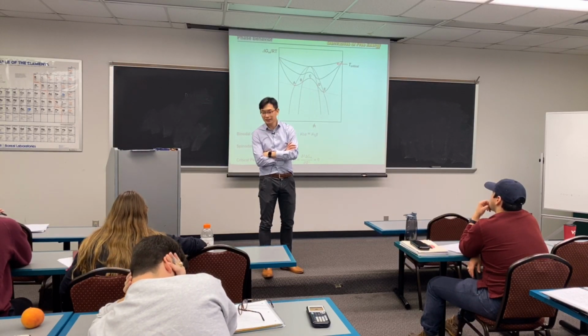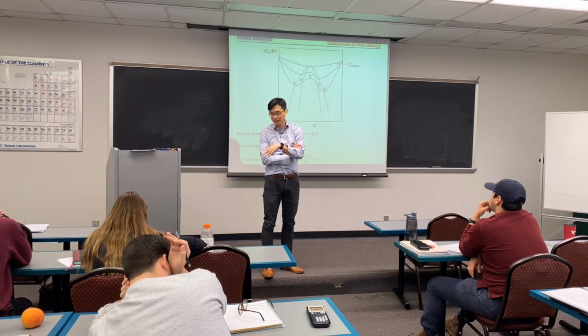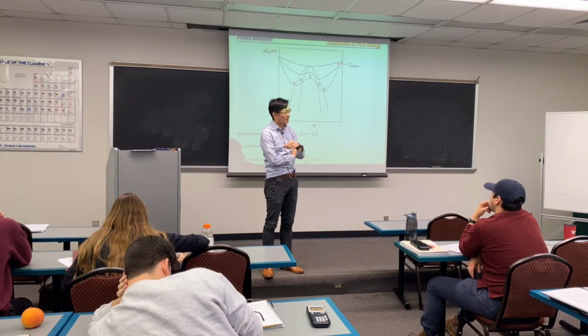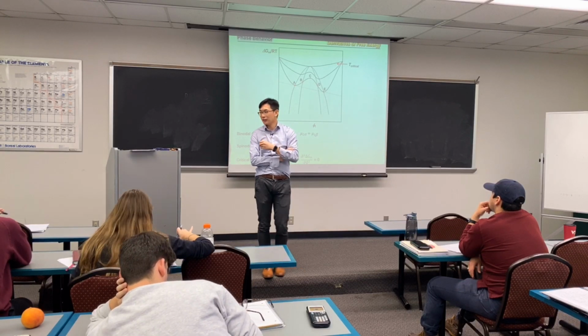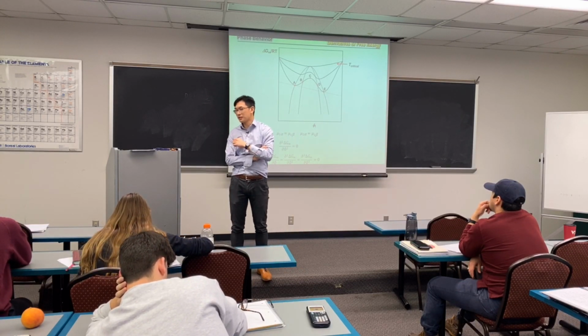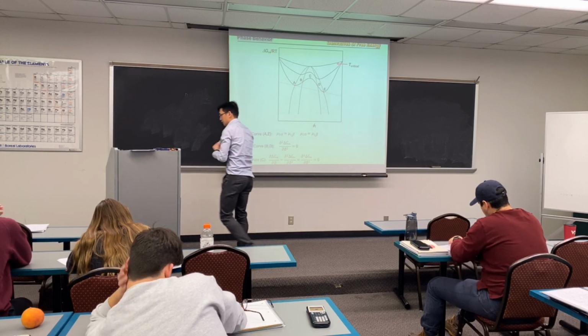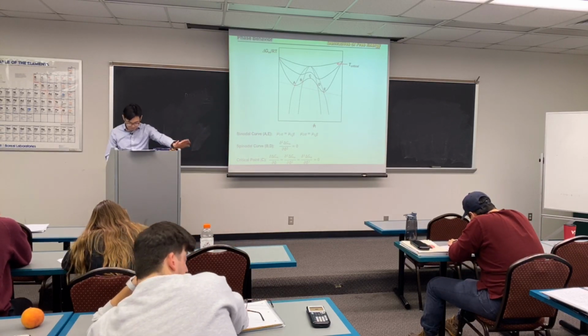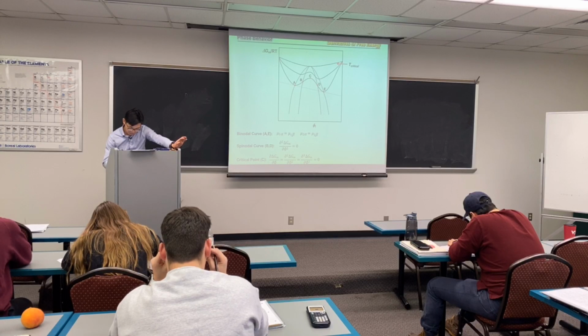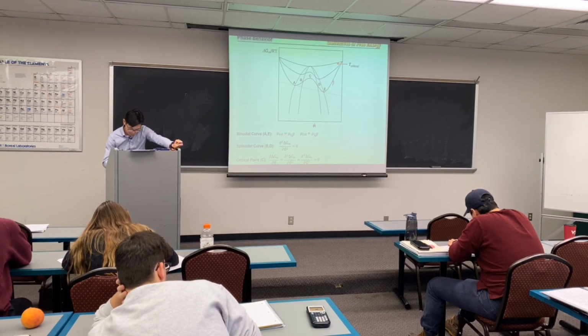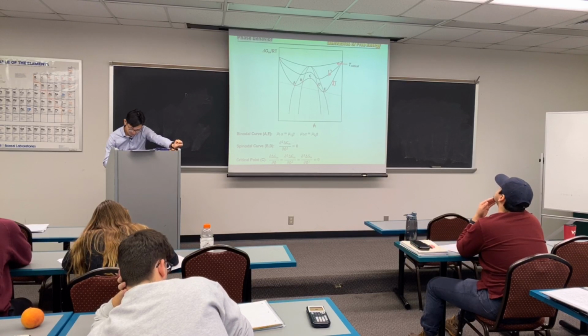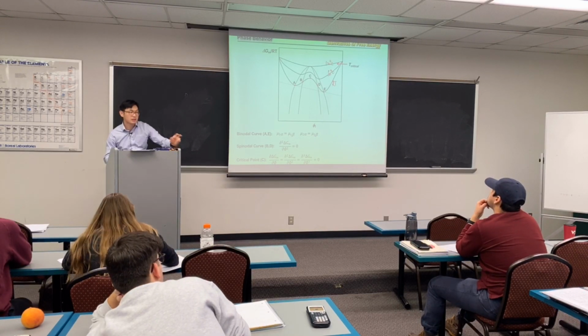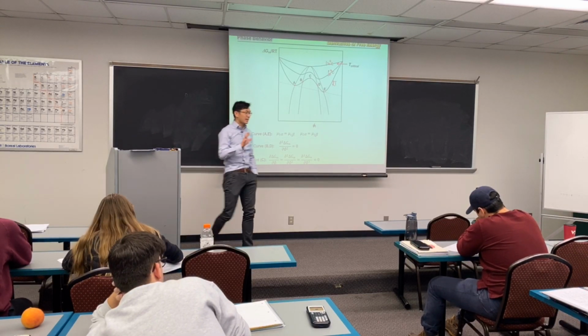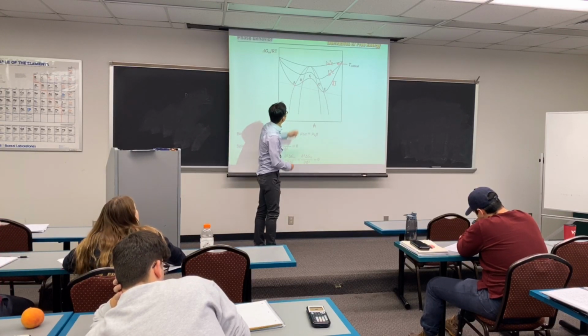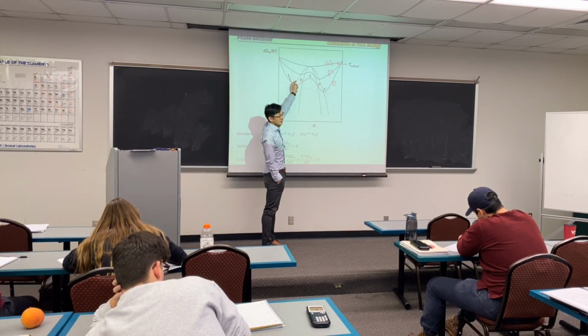The delta S, delta H. Delta S, delta H. And it's related to delta G, right? It's basically delta G at various different temperatures. So I'll give you an example. More specifically, this would be room temperature. This would be 50 degrees Celsius. This would be 100 Celsius. Just to help you understand, at different temperatures, you would have 3 different lines of delta G divided by RT.